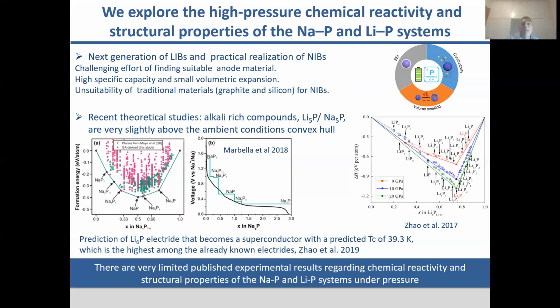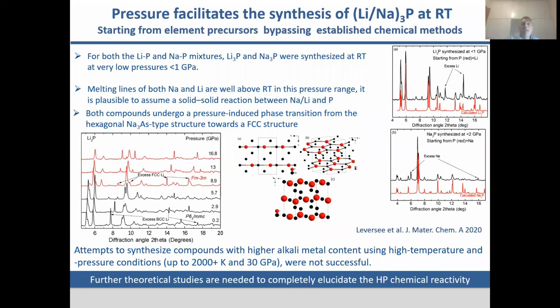Now, we managed to synthesize these compounds under pressure. Again, this was control experiments. Lithium-3 and sodium-3 phosphorus, and you can easily see it here from the X-ray diffraction, how the calculated diffraction pattern looks in the experimental pattern. Now, these compounds are stable at ambient, and one can synthesize them at ambient conditions. However, the procedure to synthesize these compounds at ambient is extremely tedious.